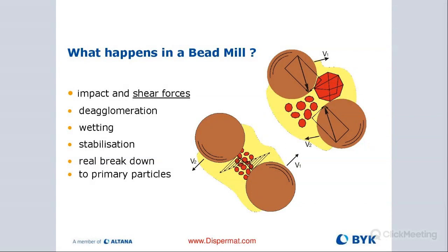So as you're milling, inside of your milling chamber, whether it's a basket mill or a horizontal bead mill, these beads drift around your slurry at very high velocities, and they get pushed towards each other, and then they drift away from each other at really high velocities. That drifting action is actually what's producing the shear. Think about it this way: if you know the rubber duck syndrome in the bathtub, as you try to squeeze that rubber duck, it always tries to escape your hands, it's very hard to actually catch. That's exactly what's happening inside of a bead mill, except at much higher speeds and a lot more force.